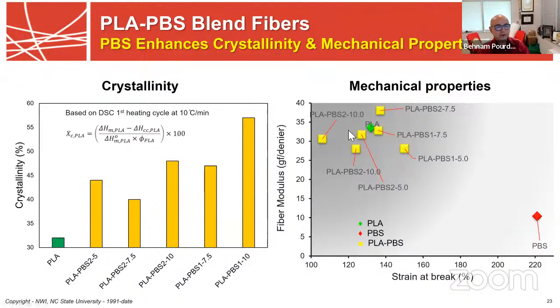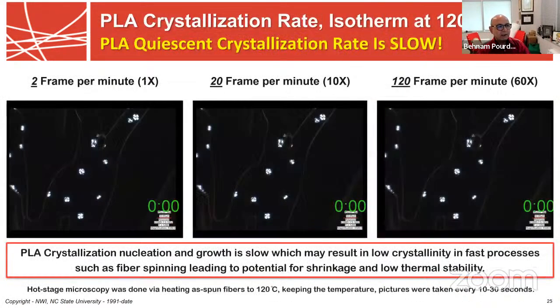And then, of course, you look at the mechanical properties of these materials, you get a really different range of behavior. PBS is pretty ductile, PLA is pretty brittle. So when you start adding these, you're actually making the PLA composite a little bit more ductile. And if you look at PBS by itself, a very, very high elongation to break, but its modulus is lower, obviously, because of that.